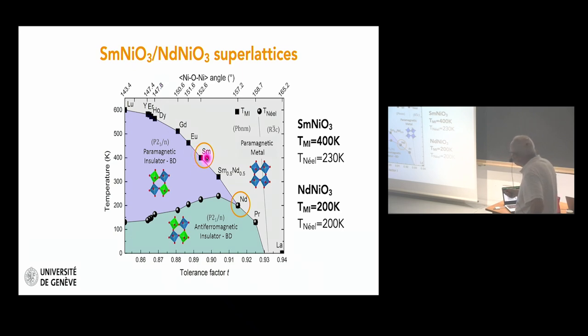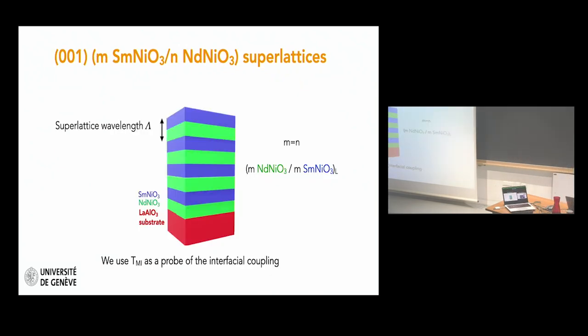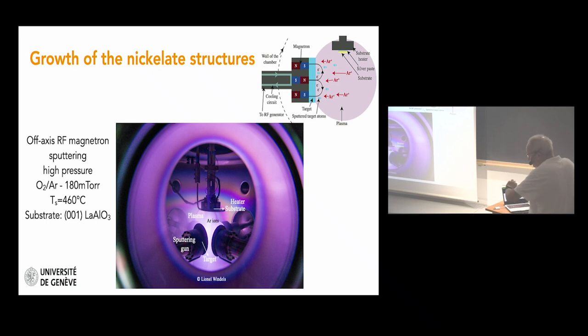So 400K for one, 200K for the other one. The Néel transition temperatures are nearly the same, but here it's coupled, and here it's decoupled. The general idea was to measure the metal to insulator transition of the system and use this information to say something about a possible coupling between the layers. These layers are grown by off-axis magnetron sputtering. You see here the system.